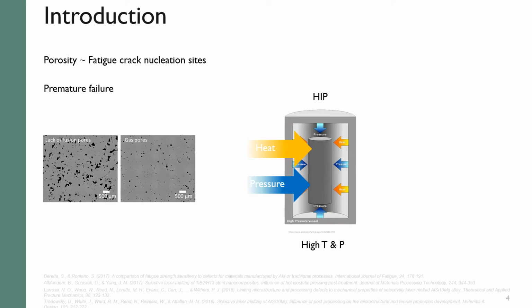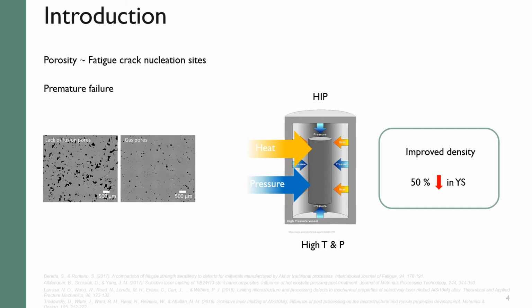It applies high temperature and pressure, helps reducing the porosity, but it also causes microstructural changes and decrease in strength up to 50%, for example, in the case of AlSi10Mg LPBF parts.